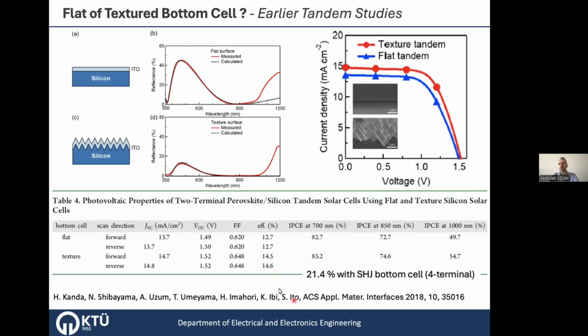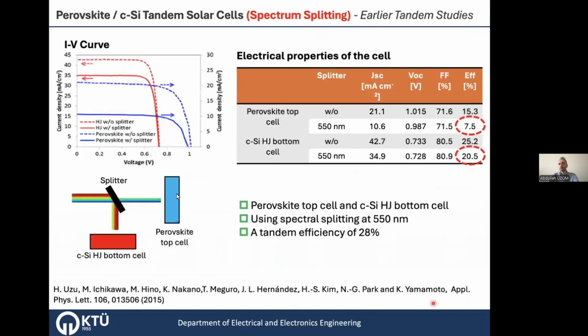This is the earlier tandem studies. Again, we continue with the earlier studies. One of the first studies of tandem solar cells is here at 2015, and at that time they used spectrum splitting. As I showed in the device structures, the splitting can be done, but it is not feasible, I guess. What they did is they split the spectrum at 550 nanometers to the perovskite and crystalline silicon heterojunction bottom cells separately, and they could reach a tandem efficiency of 28%.